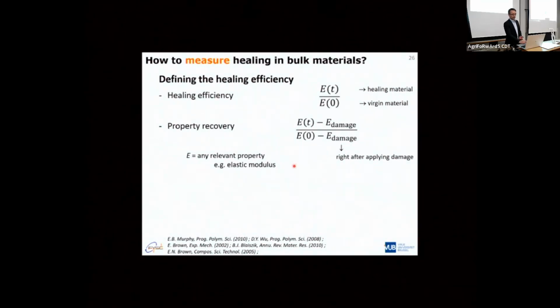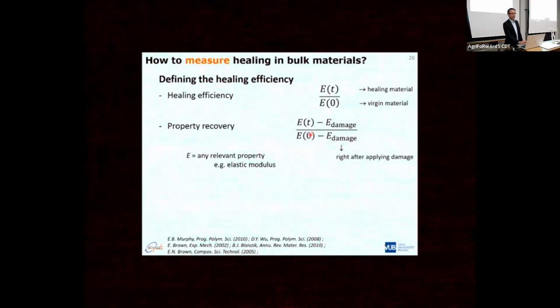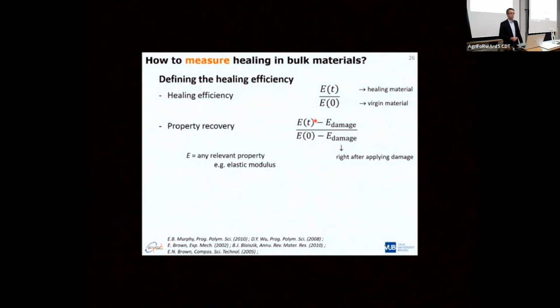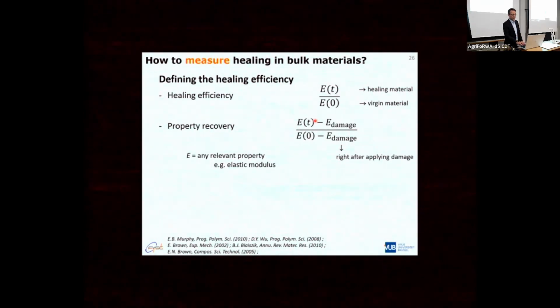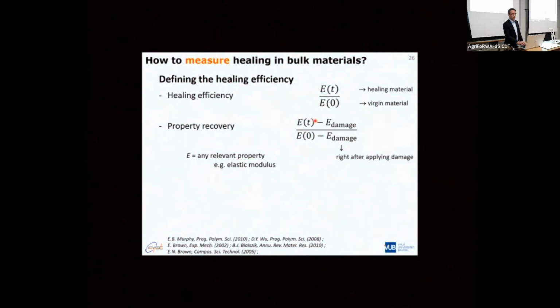You can find papers where they define it as the property of the healed material divided by the property of the virgin material. But I will show you in a minute that that might not be the most sensitive way to do it. We often use property recovery. That means that you actually look at how you are healing the damage. You take the property, the difference between the property of the virgin material and the damaged material, and you see how that difference is disappearing over time or with the healing schedules that you are applying. So this E could be a modulus, but it could also be corrosion barrier resistance or something like that.